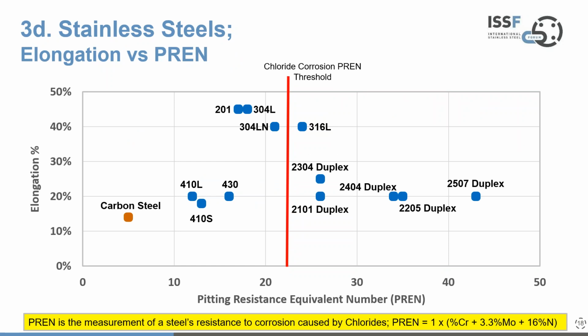Now, if I then move forward to consider elongation against the pitting resistance equivalent number, we get a slightly different picture here. So carbon steel and duplex steels are reasonably aligned in terms of elongation, duplex slightly better. But again, we know that the corrosion resistance of the duplex family is much improved. And then you get a separation of the mid-band of stainless grades. So the elongation of primarily the austenitic group is much better than the ferritic and martensitic group. And I think that's one of the features of austenitics. These are very ductile, very formable products, but you have to accept that there's always a trade-off here. You can't have perfectly all the properties all of the time.